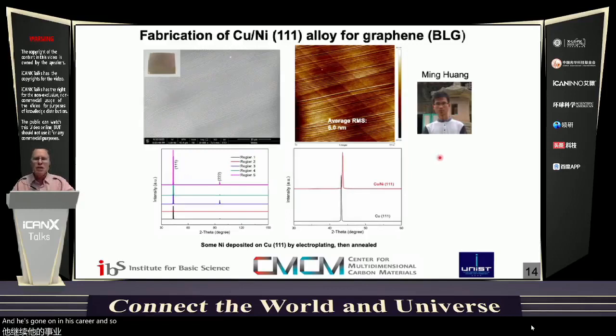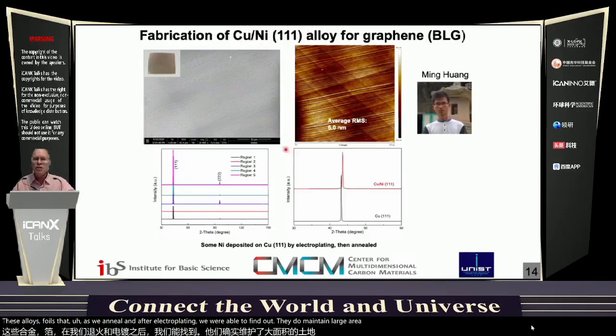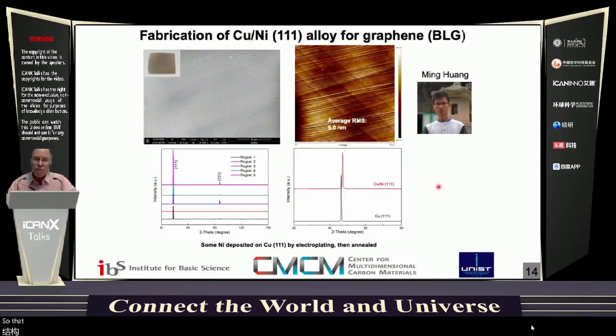And so what we did here is we took our copper foils and we electroplated nickel onto them. This is a very nice way, it turns out, to make these alloy foils that as we anneal after electroplating, we were able to find out they do maintain large area single crystal structure. So that was something we simply had to do the experiments and find out.